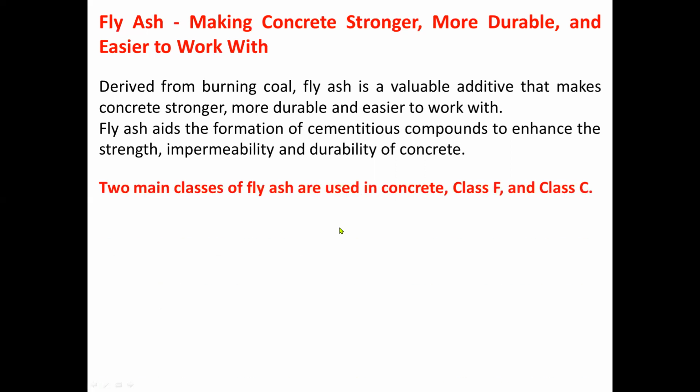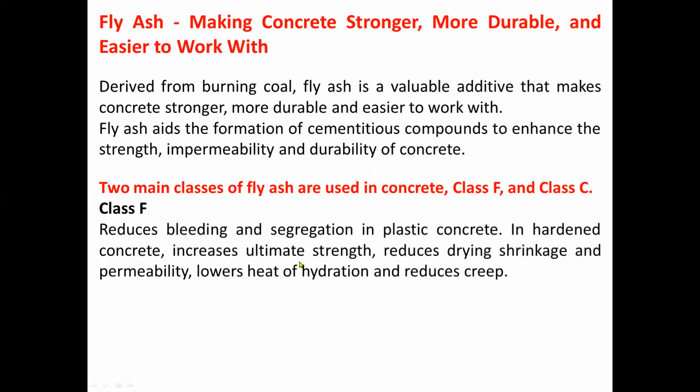Now, we have two main classes of fly ash that are used in concrete. First, we have the class F. Second one, we have the class C. For the class F, ano nga ba yung class F? It reduces bleeding and segregation in plastic concrete. In hardened concrete, it increases ultimate strength, reduces drying shrinkage and permeability. It also lowers heat of hydration and reduces creep.